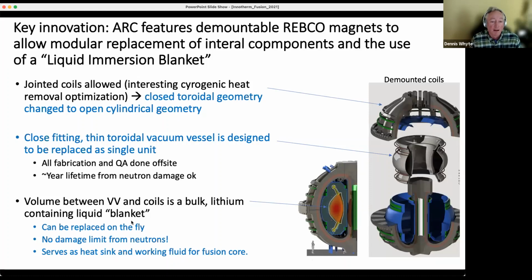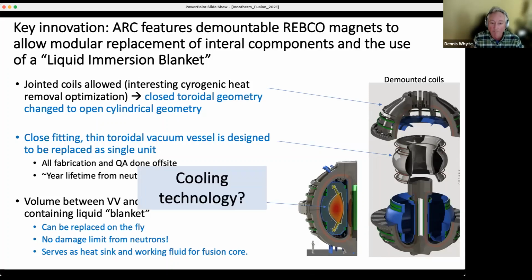And then finally, the other key innovation was that the volume between the vacuum vessel and the magnetic coils is a bulk lithium-containing liquid blanket. It's essentially a big pool of this, that's why we call it the liquid immersion blanket, because the vacuum vessel, which is the only thing the vacuum is needed for is the plasma, is on the inside and up close to it. So by definition, this can be replaced on the fly because you just pump it around. You get no damage limit from the neutrons because the neutrons can knock all they want into a liquid, but it doesn't care about its atomic ordering, and it serves as the global heat sink and working fluid for the fusion core. But what about the details of the cooling technology of this?